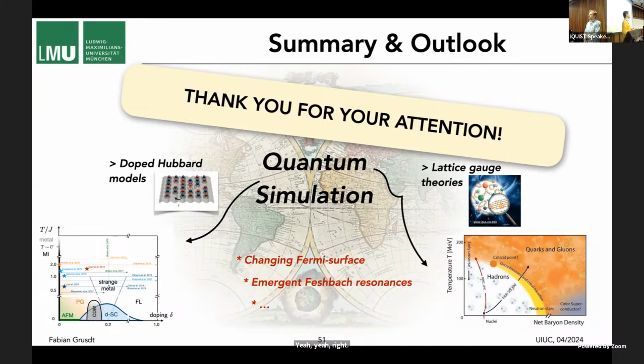But when we did quantitative comparisons, then of course it's different if we just switch off the tunneling but not the superexchange. So we also compared the spin gap to the pairing gap, or the binding energy, and we do find some differences, which is quite interesting. We also don't rely on identifying one with the other. In the numerics, we just do a spin excitation.